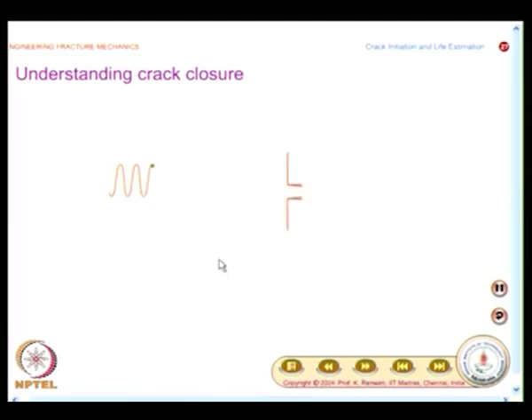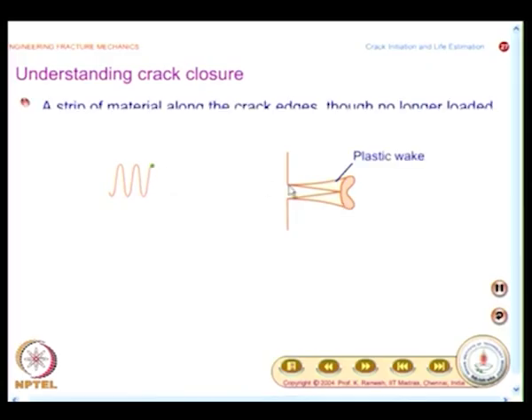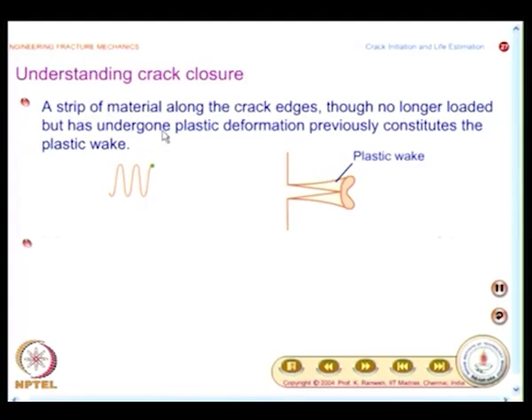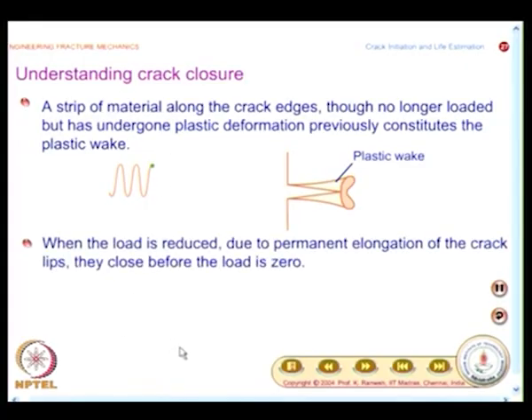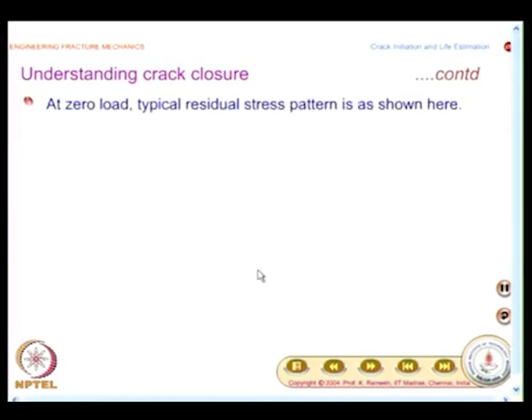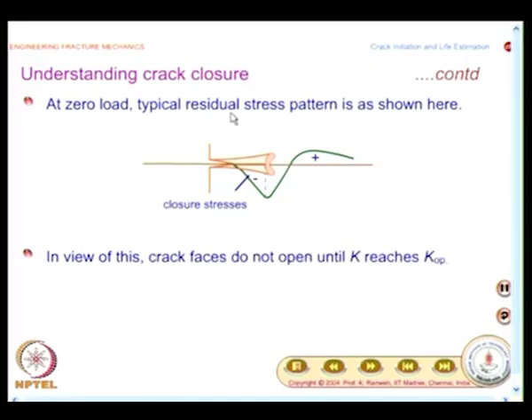And you can see the animation again. For this case, you have the plastic wake, and this explains what the plastic wake is. This shows when the load is reduced, you find that when the load is still having some value, the crack is closed. And you also have the typical residual stress pattern at 0 load, and I think I can magnify this for you.